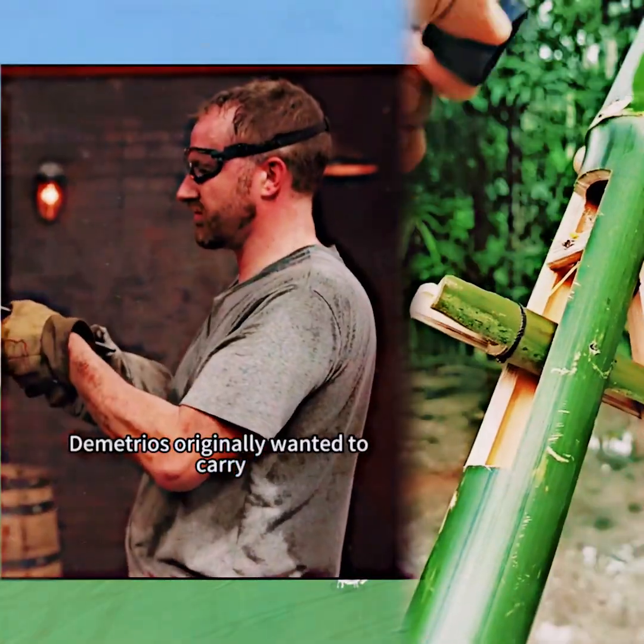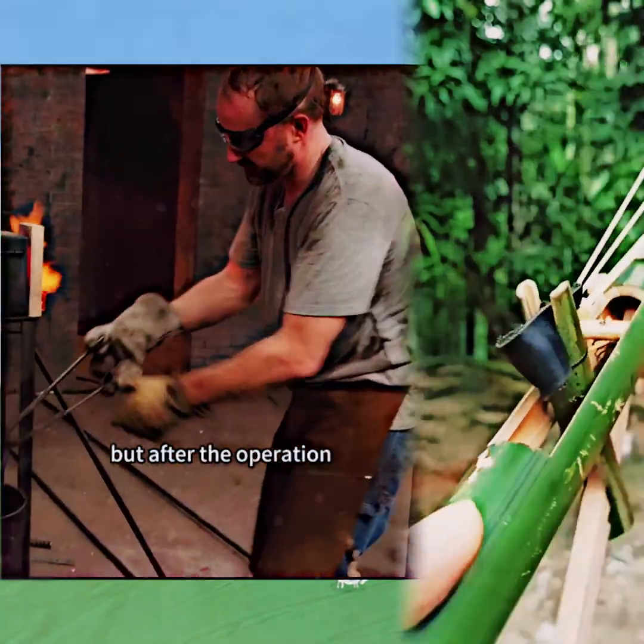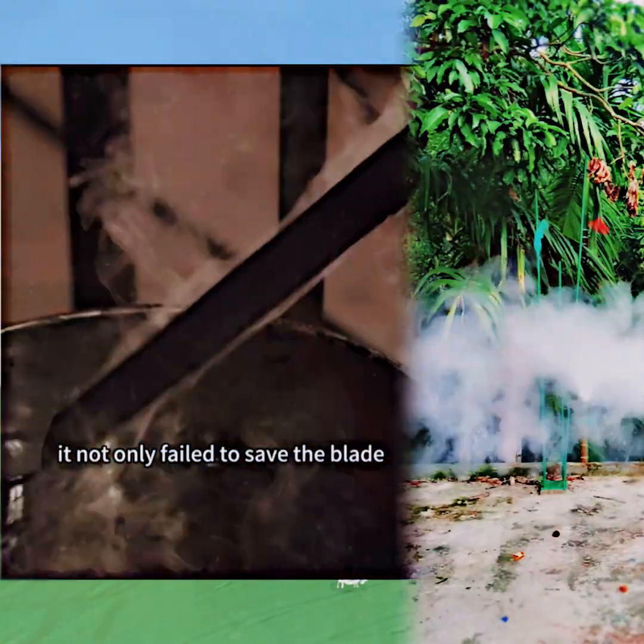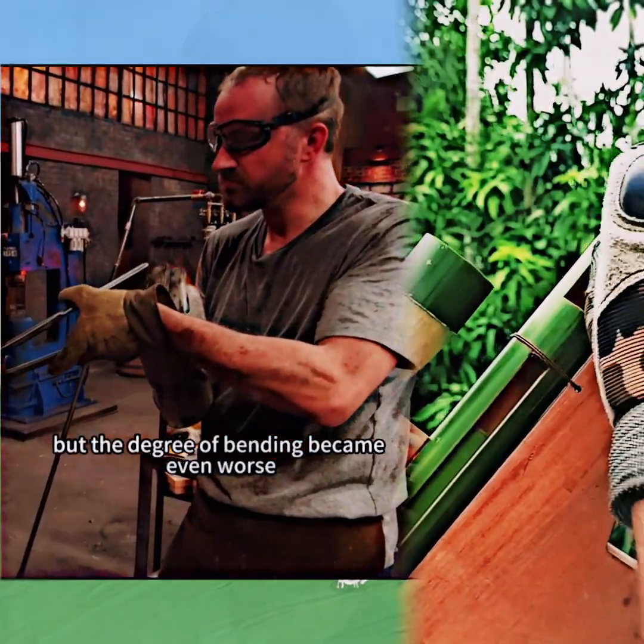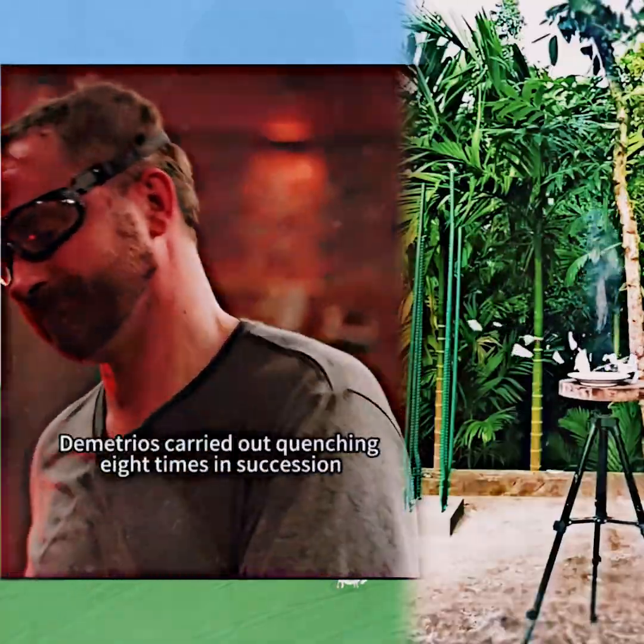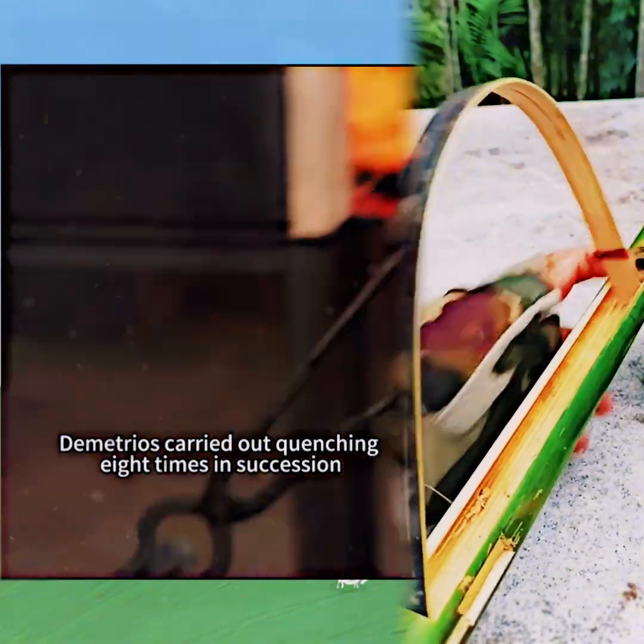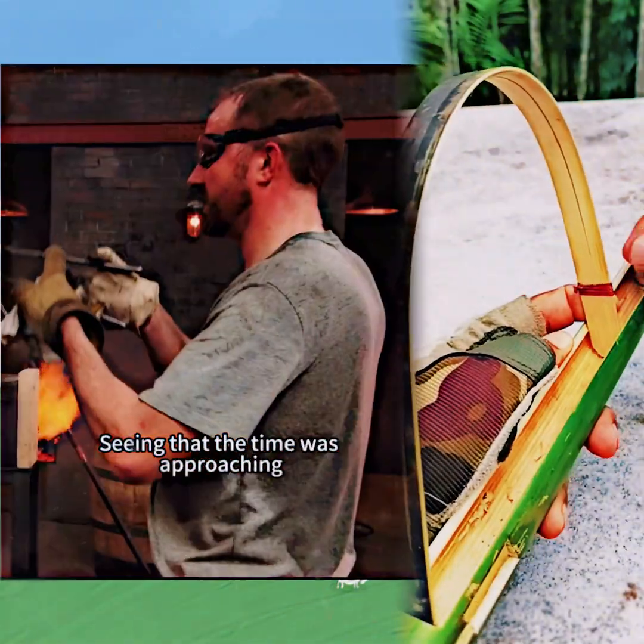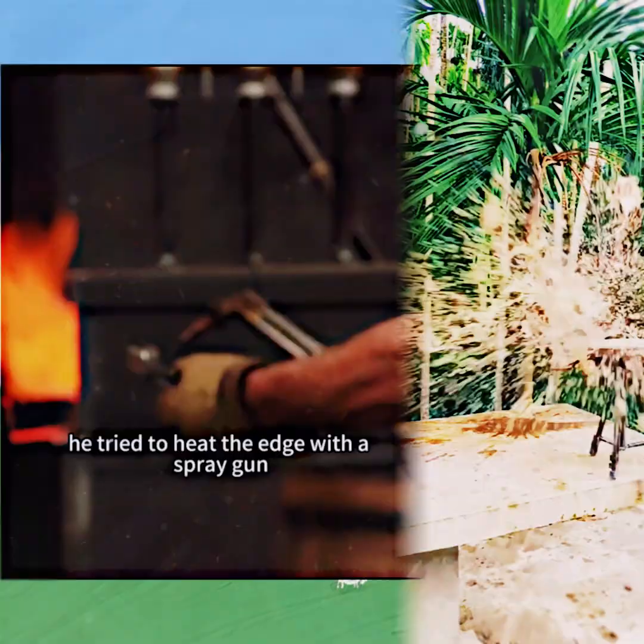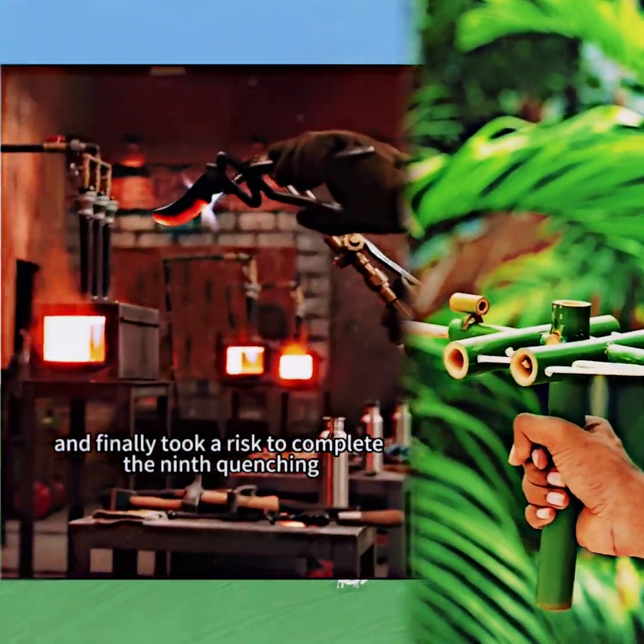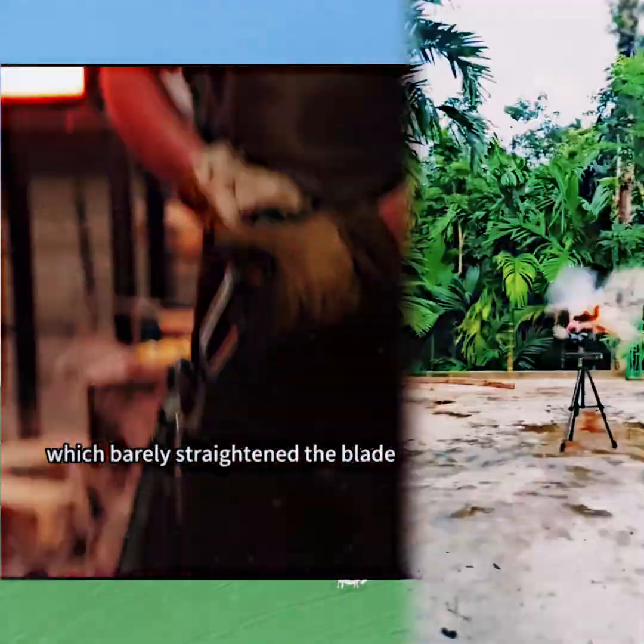Dimitrios originally wanted to carry out a second quenching to remedy it, but after the operation, it not only failed to save the blade, but the degree of bending became even worse. Next, to save the blade, Dimitrios carried out quenching 8 times in succession, but none of them could adjust the blade back. Seeing that the time was approaching, helplessly, he tried to heat the edge with a spray gun, and finally took a risk to complete the 9th quenching, which barely straightened the blade.